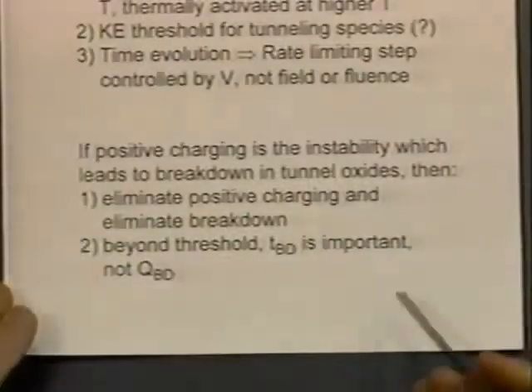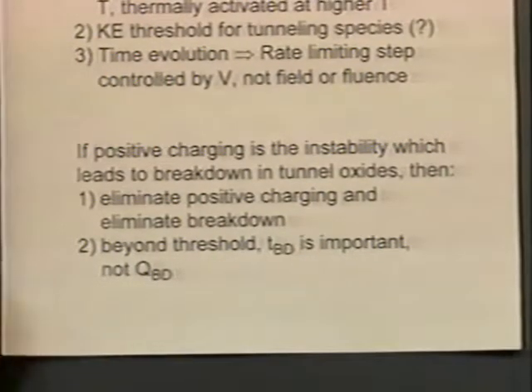But what I can address right now is breakdown of the oxide. For example, if you can eliminate this positive charging, then maybe you can eliminate breakdown if the breakdown is related to the positive charging. And certainly you can. Just stay within that threshold window. Don't put 3 volts across the oxide in one direction, 1 volt in the other direction. And then perhaps you can eliminate the positive charging. If the positive charging is related to breakdown, you eliminate that.